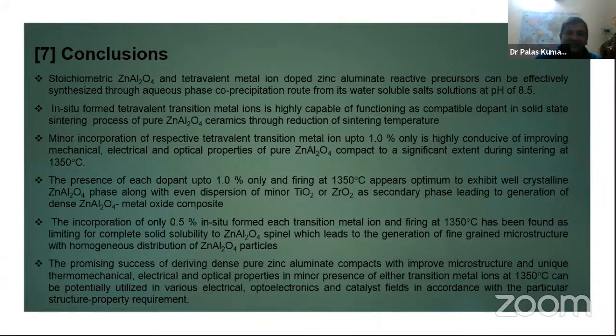Now, from the property point of view, we say that the presence of dopant up to 1% basically exhibits the well crystalline zinc aluminate phase, along with a small dispersion of titania and zirconia as a secondary phase, leading to generation of a zinc aluminate metal oxide composite. And if we analyze that, for titanium 0.5% and for zirconia 1%, from Hume-Rothery's law of solid solubility, it is very clear that 0.5 weight percent is well within the solid solubility limit, but up to 1% for zirconia and up to 0.5% titanium might be a very good option to choose for further applications.